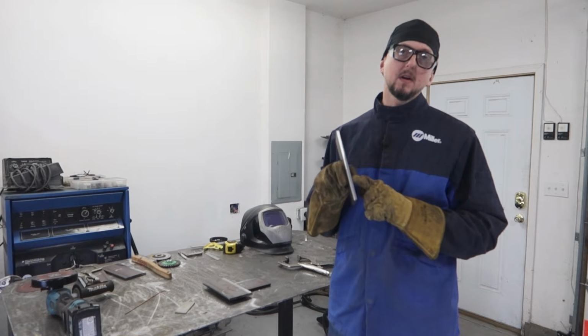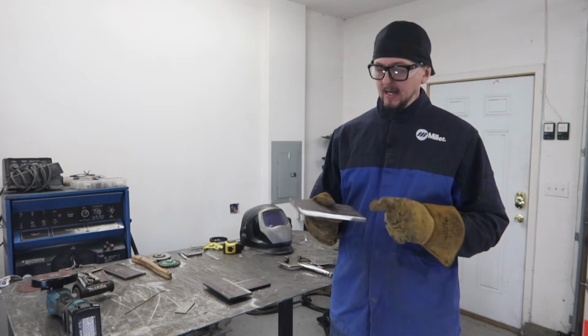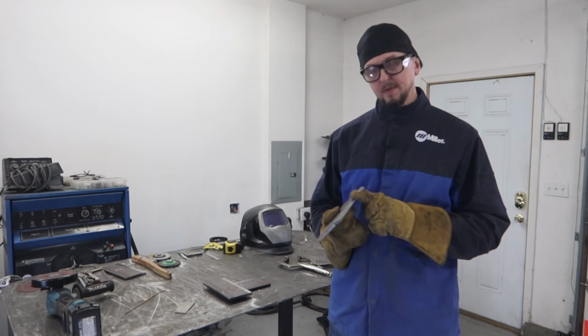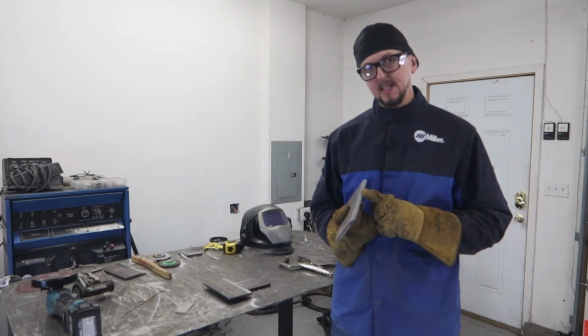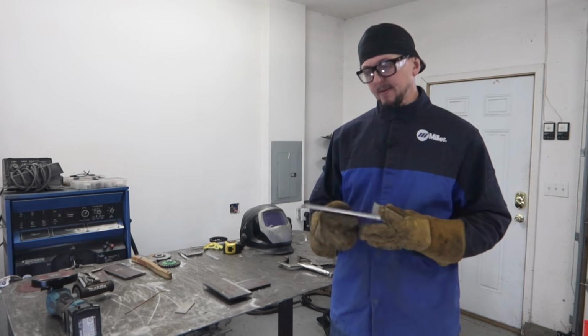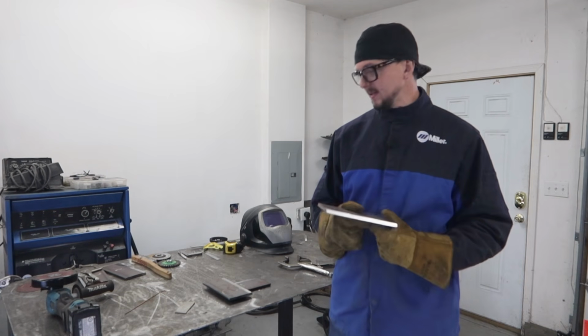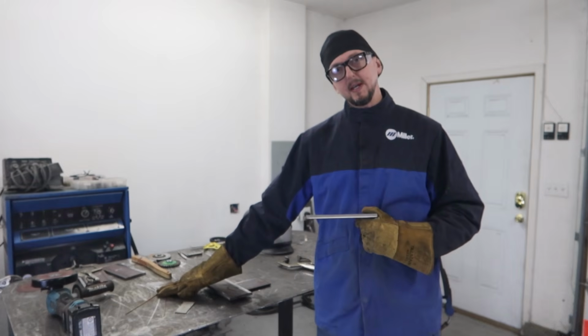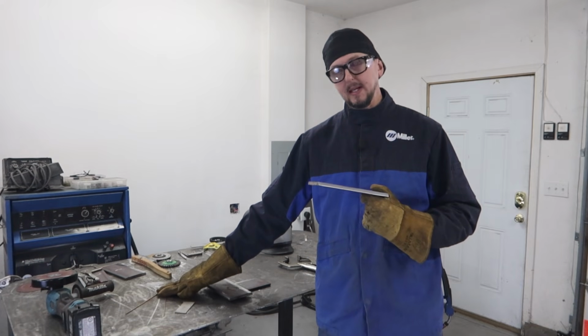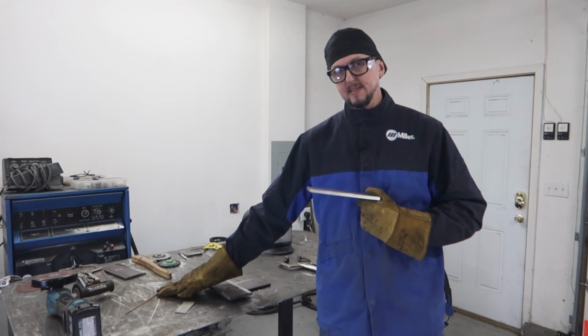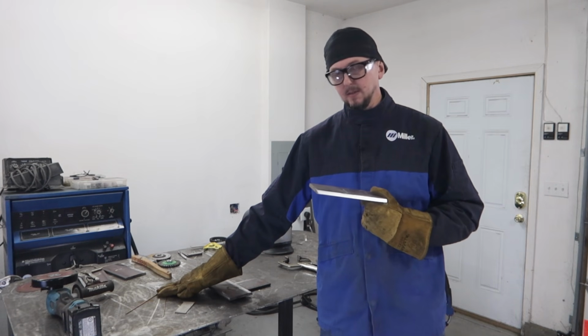Okay, so now we have our plates all prepped up, and we have a root face on there. The root face is no more than a 1/16 of an inch. And the other things that we need for our fit up is we need a spacer to space our root opening. And that's going to be 3/32 of an inch for this, is what I like to use.